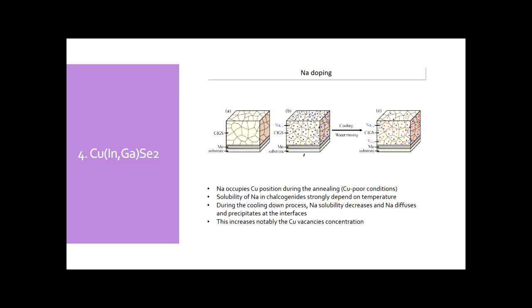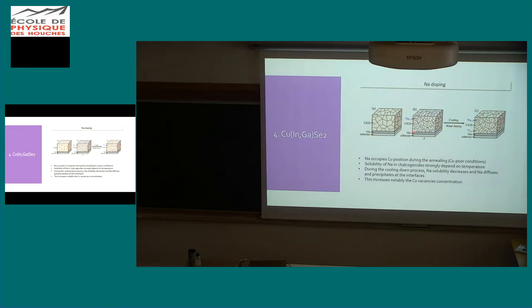And the reason was solved some years ago, when some group demonstrated that when you synthesize your material, sodium occupies the copper position, and during the cooling down process, because sodium is no longer soluble in the CIGS, it then diffuses toward the interfaces, but leaves a lot of copper vacancies. So what sodium is doing is helping to create copper vacancies to control the p-type conductivity.